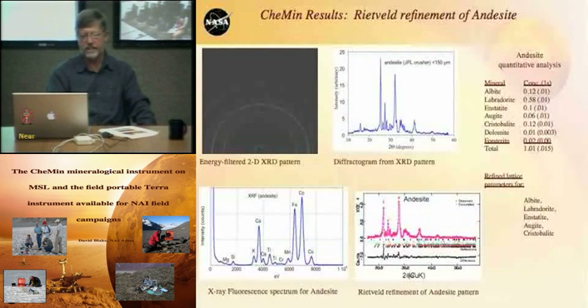Here's the 2D energy filtered XRD pattern. And here is the diffractogram that was obtained from that pattern. This is what's called a Rietveld refinement, which is a full pattern fitting refinement. And by doing this kind of a quantitative analysis, you can get a fully quantitative analysis of all the minerals that are present there. This was done by Dave Fish at Indiana University, who's one of the people on our team.